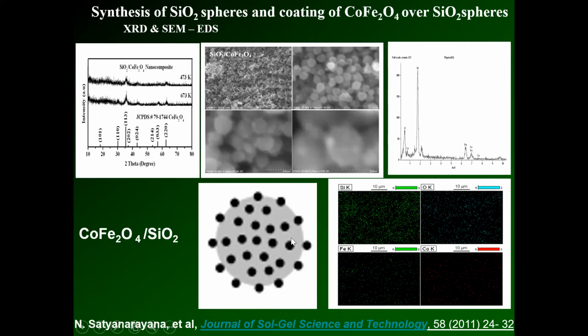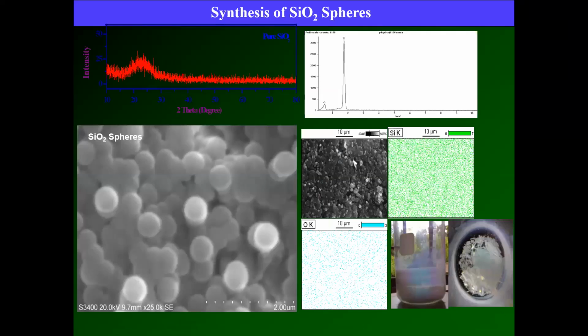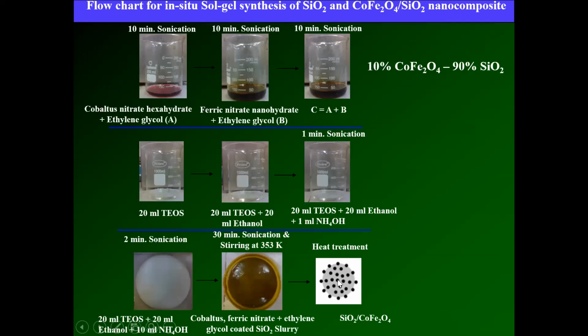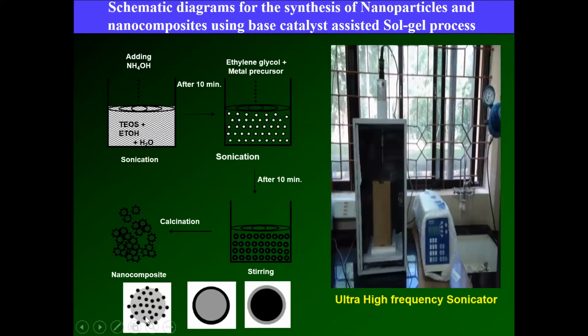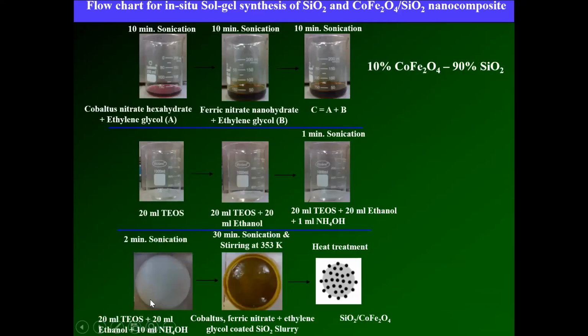So now from this we can understand the form of the nanocomposite is this microstructure. That means nanoparticles of cobalt ferrite coated over the SiO2. The cobalt ferrite nanoparticles are crystalline, polycrystalline, and SiO2 is amorphous. So it is nanocomposite form. So whatever we propose, we are able to get this type of nanocomposite microstructure compound.